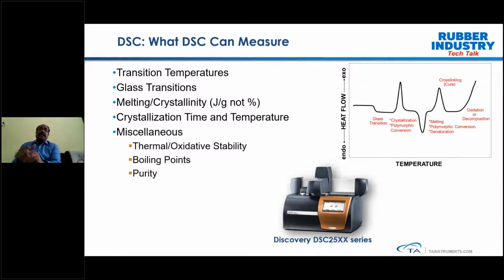So what you can see here is, if you look at the typical thermograms, whenever a sample undergoes any endothermic or exothermic activity, we can see that as a shift in the heat flow. When the sample undergoes glass transition temperature, it is observed as an endothermic step. In case of crystallization, the curve goes in the exothermic direction, so we see an exothermic peak. And if it's a melting, you can see an endothermic peak. Same way, if you are dealing with something like a thermoset, let's say a polymer rubber compound undergoing some curing process, then you can measure the cross-linking by measuring the exothermic reaction. And further, anything to do with oxidation you can measure from the oxidation part, like in case you wish to do an OIT application.